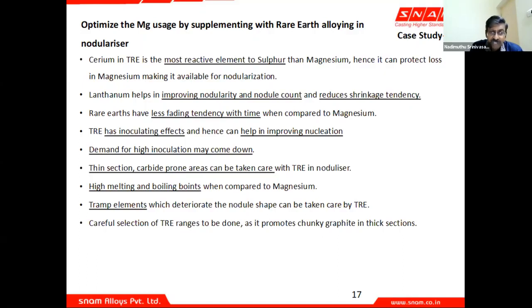Rare earths therefore have less fading tendency with time compared to magnesium because they are more stable. They have inoculating effects also. The demand for a higher percentage inoculation may come down when you combine a rare earth into your magnesium alloy. They have high melting and boiling points when compared to magnesium and are stable. The tramp elements which deteriorate the nodular shape can be taken care of by the rare earth. When I say TRE, it is a combination of cerium and lanthanum, called the total rare earth. Careful selection, however, has to be done because in thick sections, a higher cerium can lead to chunky graphite.